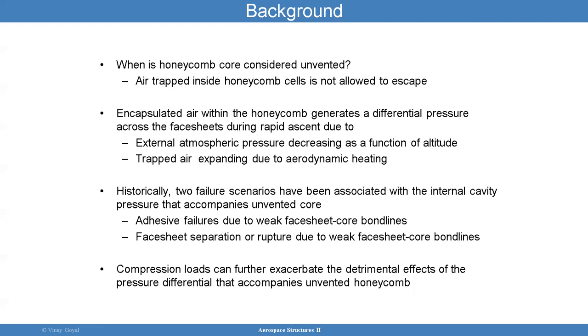There are historically two failure scenarios associated with pressure that stays in the internal cavity. The first is that you could have a face sheet to core weak bond line. The second is that the face sheet could have some sort of initial delamination between the face sheet and the core, which when pressurized can cause a bubble that can then propagate to failure. If you have a compression load in addition to the pressure inside the core, that can make the situation even worse.